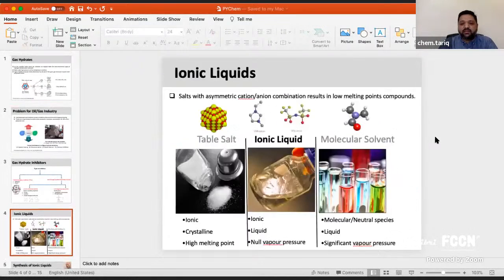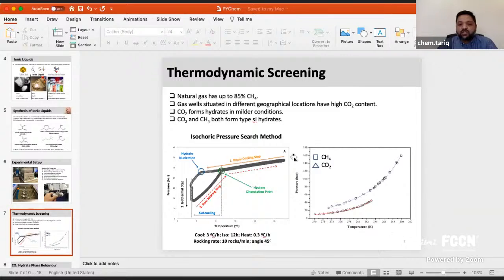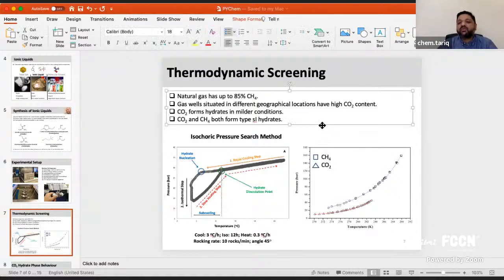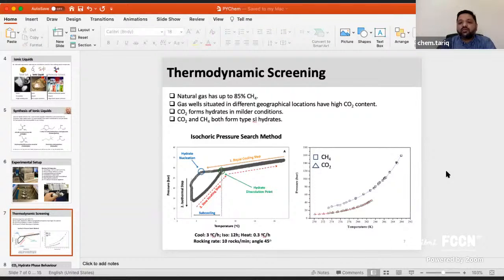I can show you. Here, as you can see, when you are cooling the system, the pressure is also going down because the temperature is going down. And then afterwards, you have a sudden drop in pressure. So there is the nucleation point, but it's not really actually the nucleation, because nucleation occurs somewhat before that. So it's quite difficult to know the exact point. That's why we always talk in terms of the onset of nucleation. So there's no data yet from the theoretical point of view. Computational models can be used and you are going to do it, but you still haven't found the time yet. Okay. Yeah.